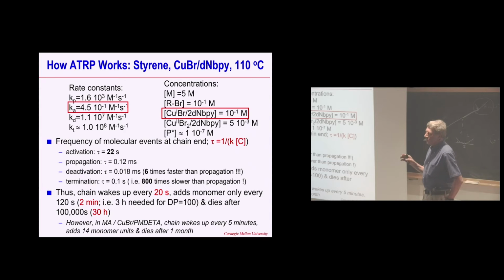Maybe a little bit about the frequency of these reactions. Normally, the frequency of a chemical reaction is the rate constant times concentration. For a bimolecular reaction, it would be the product of the rate constant and the concentration of the other reagent. So how quickly do I activate this polystyrene dormant chain end? I look at the rate constant of activation, 4.5 10 to minus 1, and the concentration of activator, 10 to minus 1, product 4.5 10 to minus 2, reciprocal value 22 seconds. So every 20 seconds, a chain wakes up.